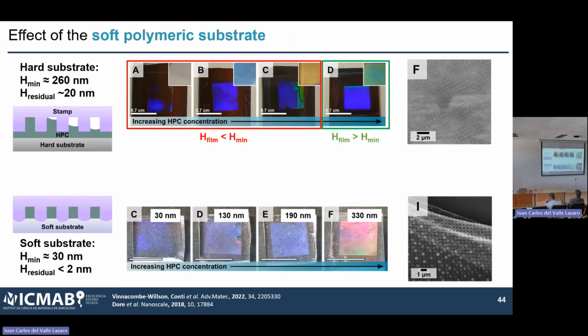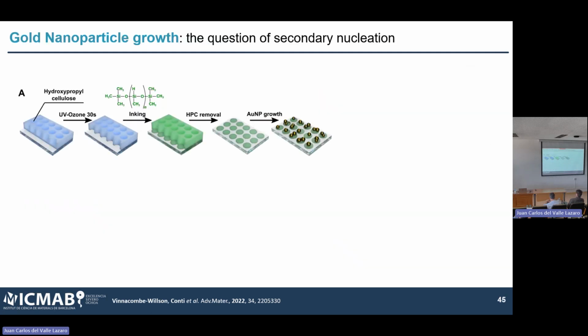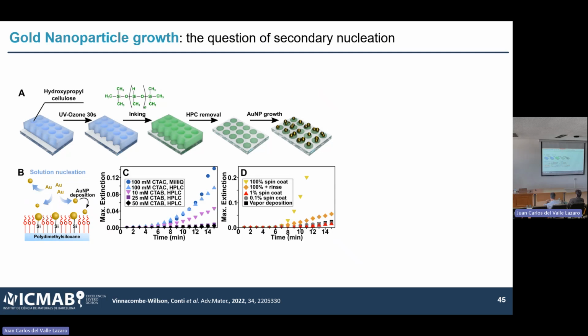And the other good thing that it's important to mention is that here you see there's no residual layer, or a very minimal residual layer. And this is extremely nice because we don't have to do a reactive ion etching step to eliminate the residual layer. We only do a UV-ozone etch of 30 seconds to make sure that we expose the surface. Then we apply our chemical ink by spin coating, and then we remove the HPC with water, and we're ready to grow the particles.